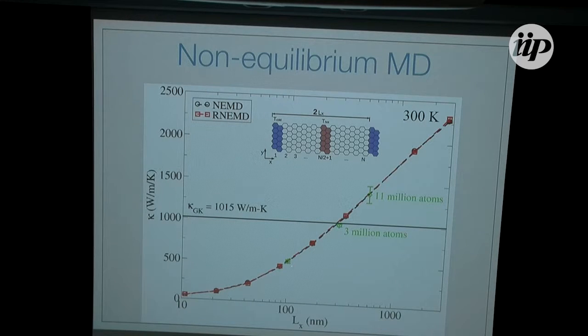So I went back and performed simulations with square patches of graphene, so the length equals the width, right? But still with this hotter area in the center. We did simulations with up to 11 million atoms. This was done on the Blue Gene with 64,000 cores. And clearly, we still have the same trend. So it really looked like the thermal conductivity does scale with the log of the system length.